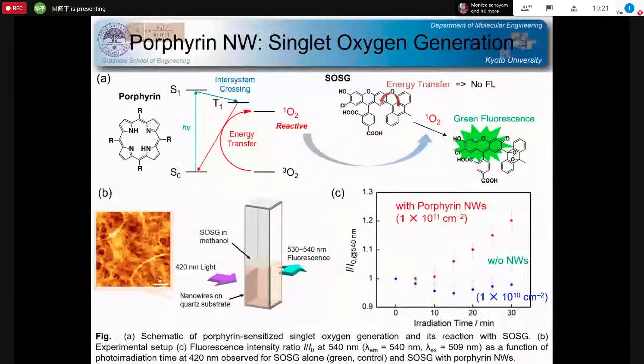And as you may know, in our case, the sizes of the nanowires are completely under control. The length of the nanowires is completely uniform, because the nanowires are generated from the top surface to the bottom surface of the thin films of the target. So we can control the size precisely over any range. Such size-controlled nanowires can also be very effectively captured by living cells. So this is the reason why we claim that our nanowire system is also applicable in the future as a medical treatment system.